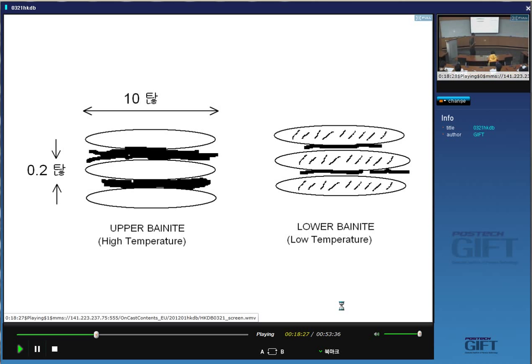high-strength steels. And that's why, if you look at structural steels, they will have low carbon concentrations if they are accelerated cooled, to generate bainitic microstructures. They will always have carbon, usually less than 0.05 weight percent, okay, if you are doing accelerated cooling. The strength comes from the very fine scale here. You cannot achieve a quarter micrometer grain size by thermomechanical processing or in the normal way. Here, you just achieve it by phase transformation. But this is a bad phase.